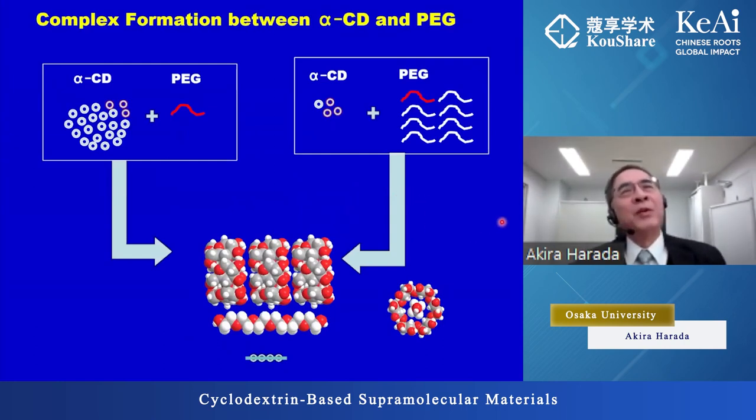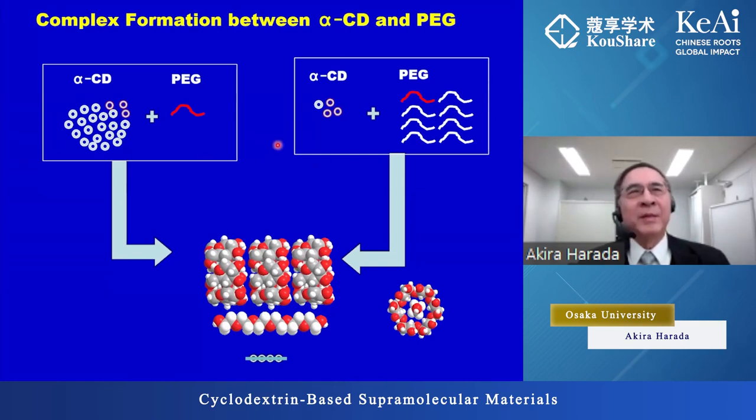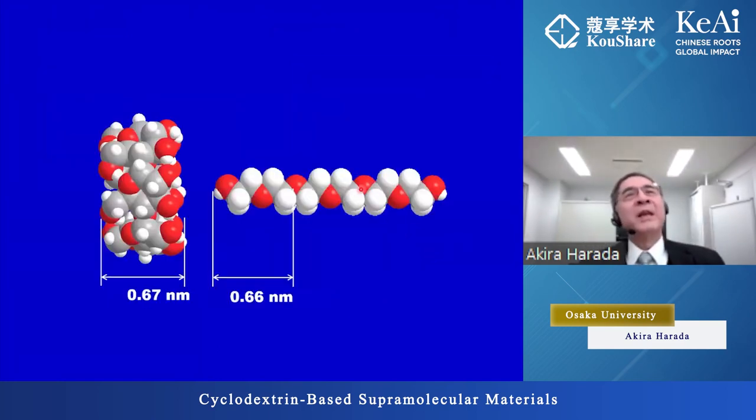And then, when you mix the alpha cyclodextrin and the polyethylene glycol in any ratio, even if an excess amount of cyclodextrin or an excess amount of polyethylene glycol is used, in both cases the products are the same. Two ethylene glycol units are bound to a single alpha cyclodextrin. Very unique. What happened? The length of the two ethylene glycol units is 0.66 nanometer, which corresponds to the